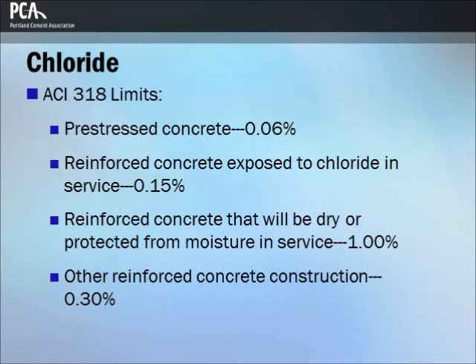Concern over a high chloride content in mixing water is chiefly due to the possible adverse effect of chloride ions on the corrosion of reinforcing steel or prestressing strands. The acid-soluble chloride ion level at which steel reinforcement corrosion begins in concrete is about 0.2% to 0.4% by mass of cement. Placing an acceptable limit on chloride content for any one ingredient, such as mixing water, is problematic considering the variety of sources of chloride ions in concrete. An acceptable limit in the concrete depends primarily upon the type of structure and the environment to which it is exposed during its service life. Concentrations of 20,000 ppm of sodium chloride are generally tolerable in concrete that will be dry in service and has low potential for corrosive reactions.